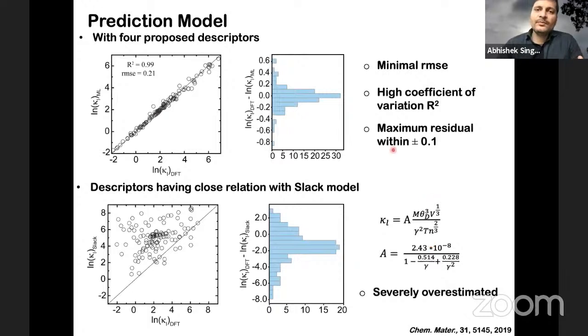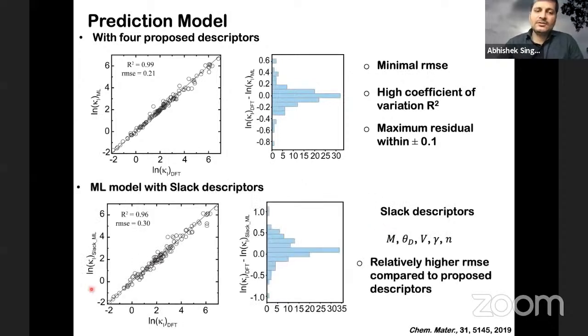So what if we use these features and build a machine learning model? And what we found is that now it works very, very well. So the empirical or semi-empirical formula of Slack has problems, but its descriptors are pretty good. And you could see that we get a model which is very good, though not as good as what we found with our descriptors. So sometimes machine learning can help to improve some of the semi-empirical models which do exist. As you know, a huge amount of approximation goes behind any semi-empirical model, and that can be corrected using machine learning.